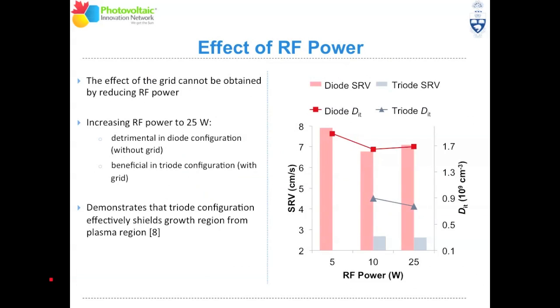The question then arose: could we achieve these same really good passivation and bulk film properties in the diode configuration by simply changing the RF power, changing the pressure to be able to control the energy or types of precursor species that are involved, just using the diode configuration without the grid? And we found we couldn't. We couldn't achieve those same excellent properties that we had with the triode configuration with the diode configuration.